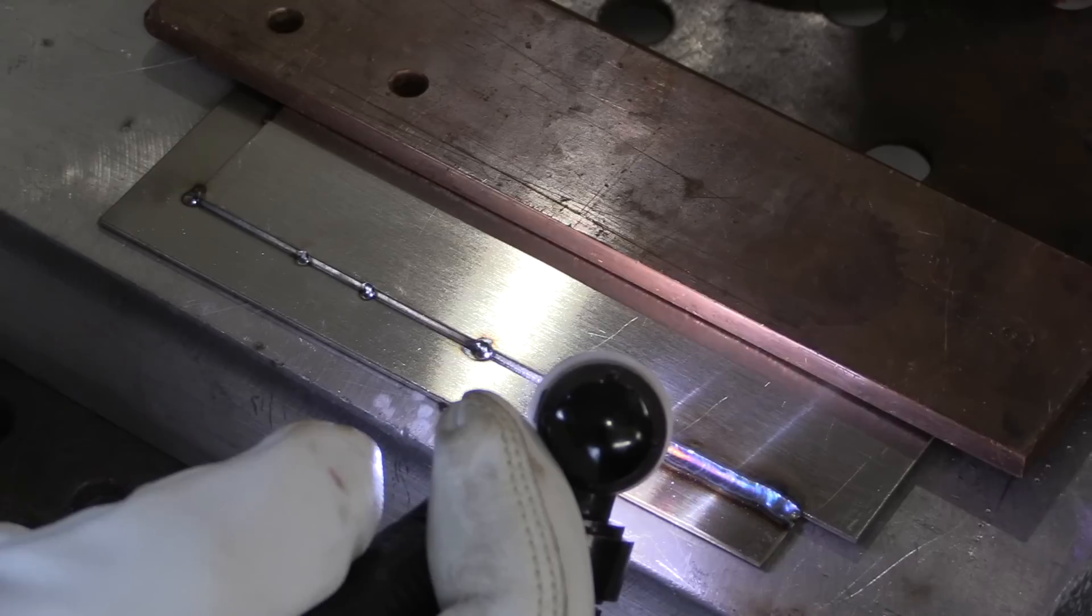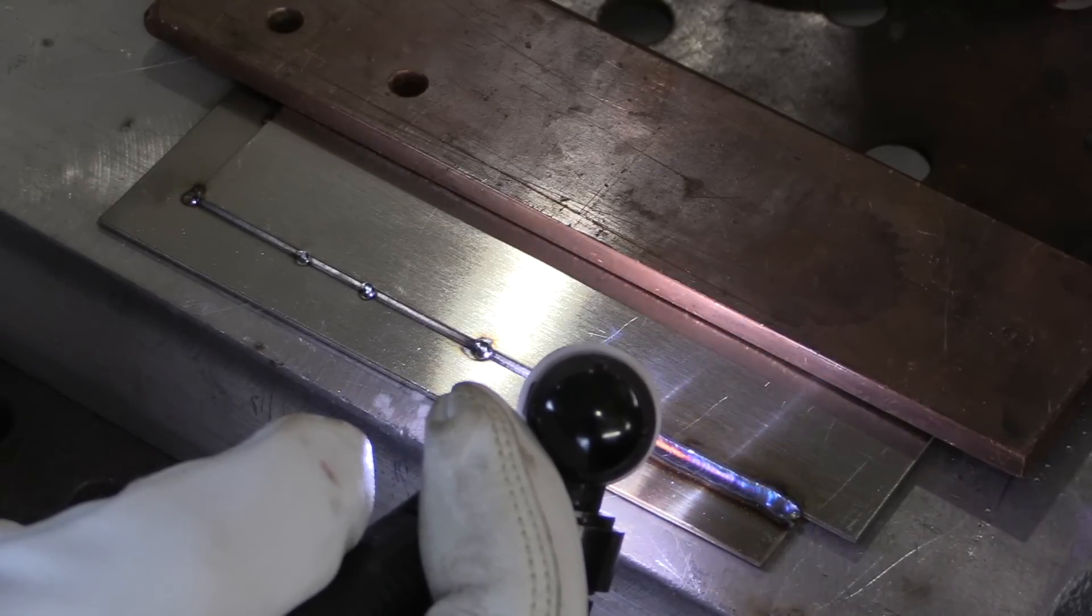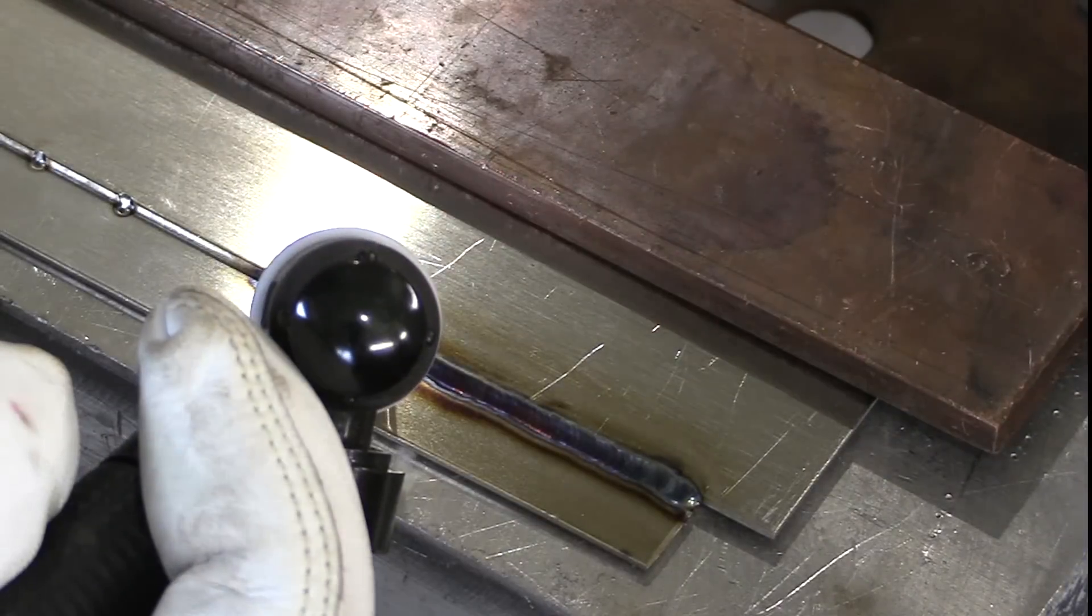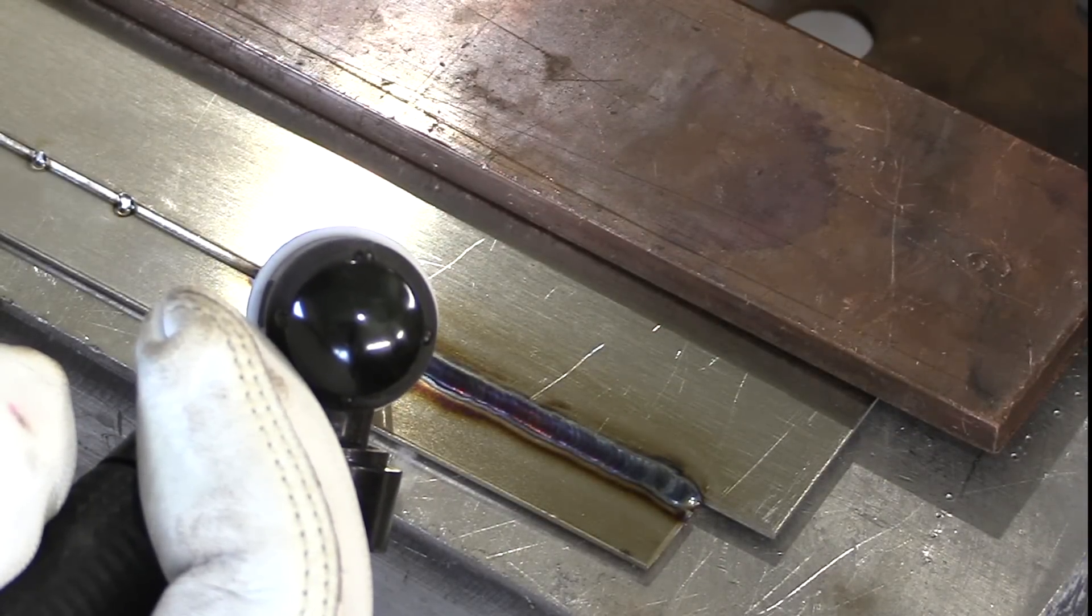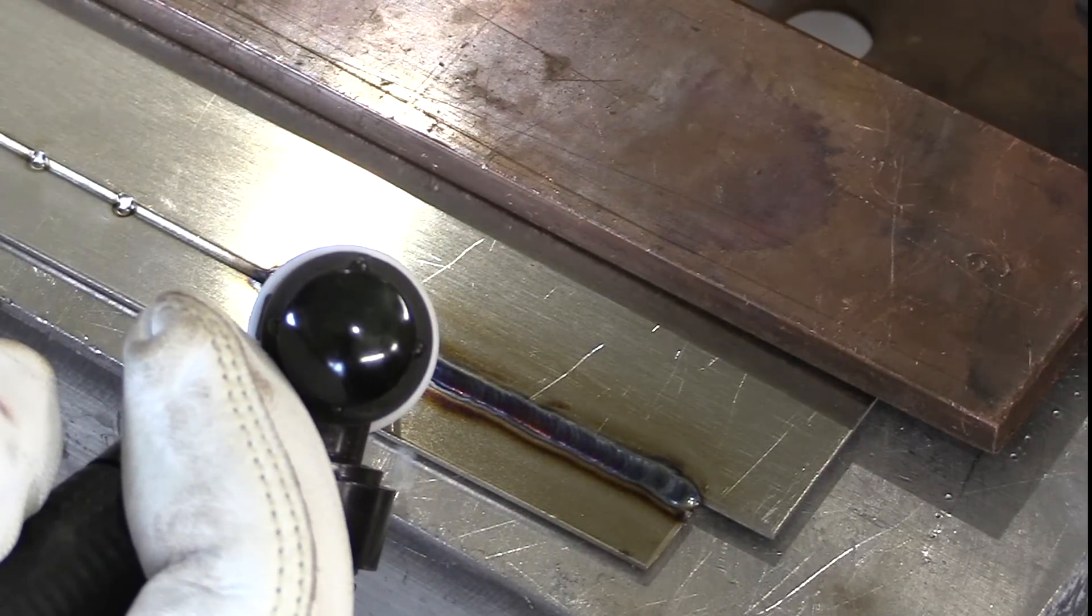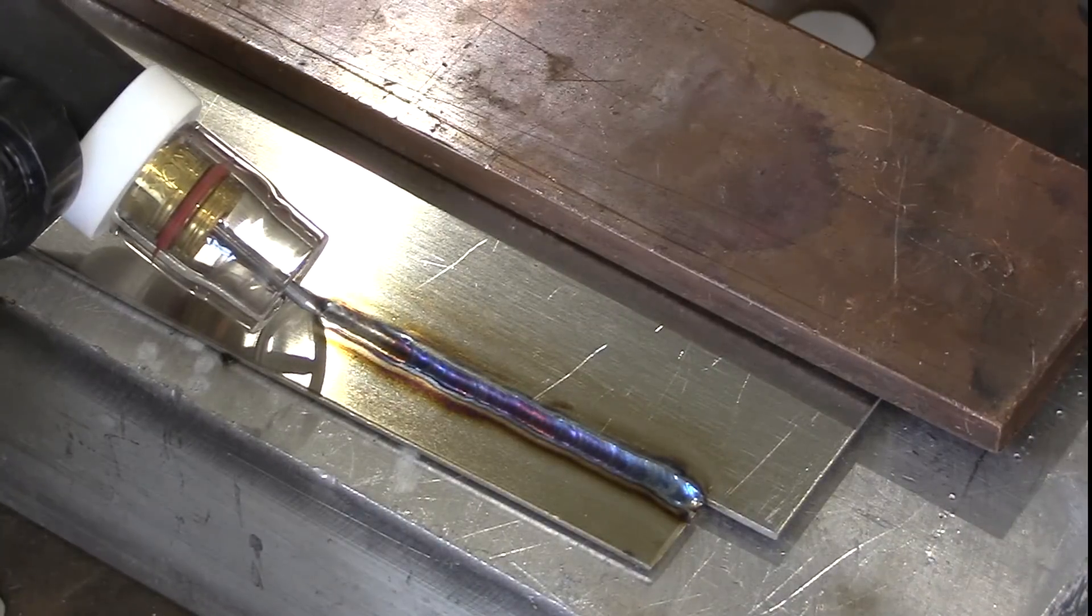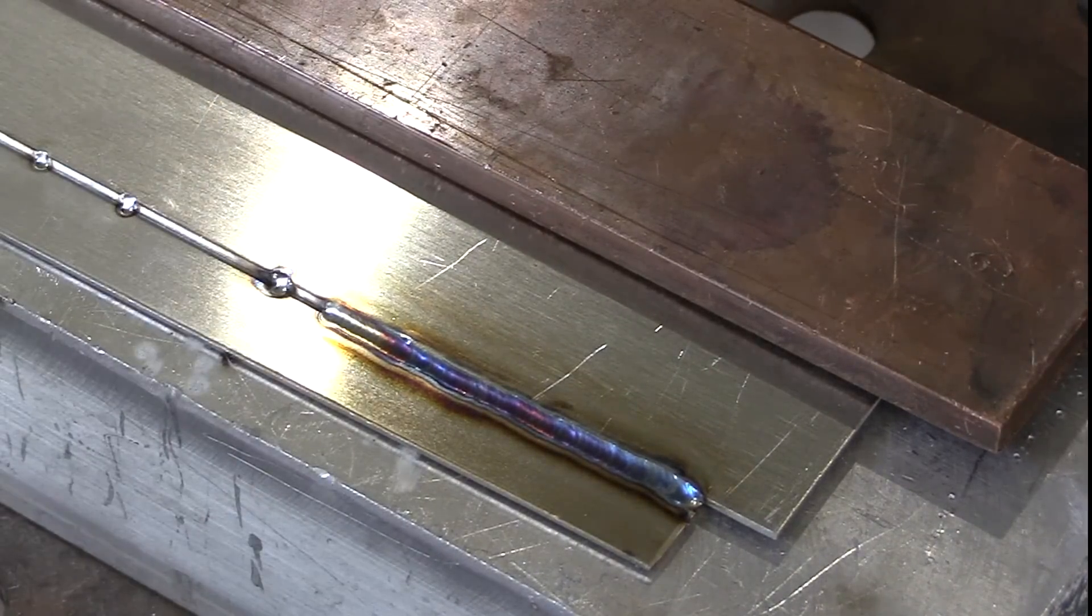I'm just using the very corner of that metal for filler metal. Basically, I'm trying to do it—the reason I'm going forward and back is because that's kind of a good gauge on when you're hot enough or not hot enough. If the puddle doesn't come with you, you need a little bit more amperage or you need to tighten up your arc. And if it's coming with you each time, you can kind of just back off the pedal until you're at the low side of the amperage, because you don't really want to burn through on a joint like this. That's kind of one of the goals—you don't want to melt through. So that's no pulse at 40 amps full pedal.